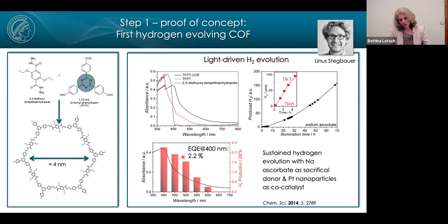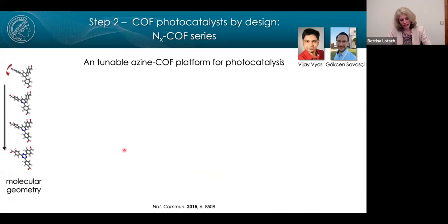Of course, then we wanted to take full advantage of the tunability of covalent organic frameworks, because after all, this is the hallmark of COFs. And so what we did is we designed an azine COF platform composed of 4 members, and these members only differed in the building blocks, where the building blocks differ by the number of nitrogen atoms that are inserted into the central aryl ring.